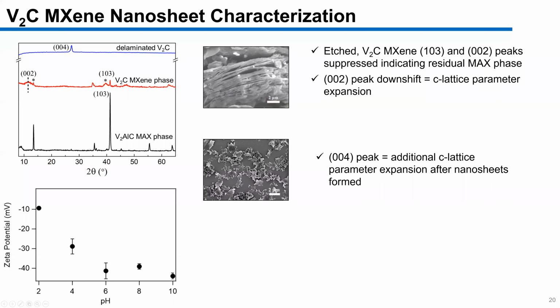We were also curious about its surface charge in solution. On this figure, on the y-axis, we have the zeta potential or surface charge of the vanadium carbide nanosheets as a function of pH. And as you can see, over a very broad pH range, the material is negatively charged. We weren't too concerned about this because it's very well known that adsorbents like graphene, which is similar to these V2C nanosheets, and activated carbon are very effective at adsorbing PFAS like PFOS, even though a lot of PFAS in water tend to be negatively charged. Where you would expect electrostatic repulsion, the large surface area of these graphitic or carbonaceous materials is able to overcome the electrostatic repulsion and result in adsorption of PFAS onto those substrates. So we measured this, but we weren't really concerned about the negative charge of V2C.